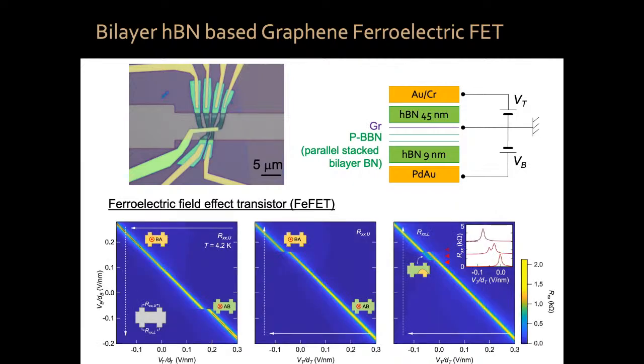So you can do this in a continuum manner as a function of bottom gate and top gate. You can see that you switch, and this resistive peak abruptly changes when you go from BA to AB type of stacking. If you then reverse, it switches at a different point. That is the hysteresis. Every now and then we're lucky and we catch a domain wall sweeping through our contact, so we see a bistable, the two resistive states. Now, this is so far 0 degrees.